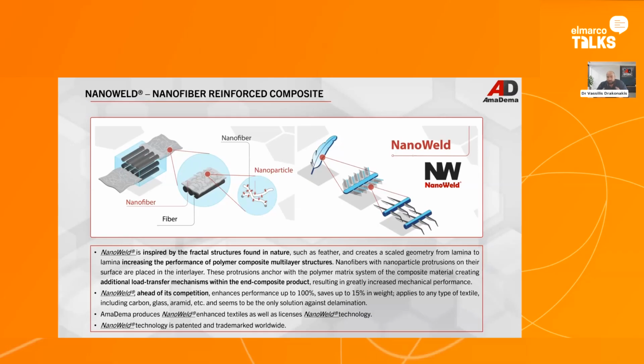So how did we come up with NanoWeld? We got inspired by fractal structures found in nature, such as the feather. And as the feather goes from the rachis to the barb and then to the barbules, we basically go from lamina to lamina. We inserted those enhanced nanofibers in the interlayer, going from the fiber to the nanofiber and eventually to the nanoparticle. This very well connected structure of the fabric, which is repeatable from lamina to lamina, transfers the load more efficiently than basically only with the fiber.